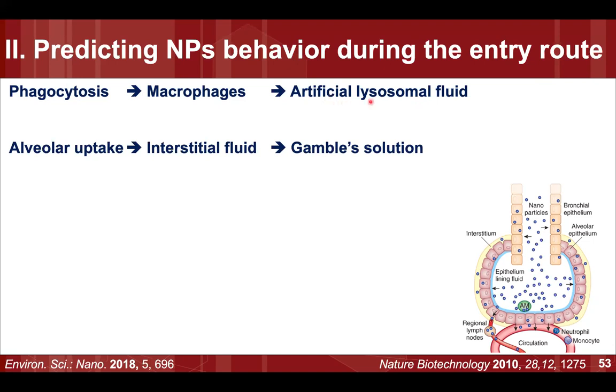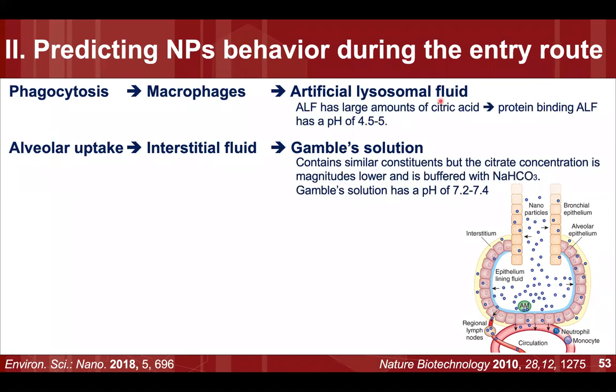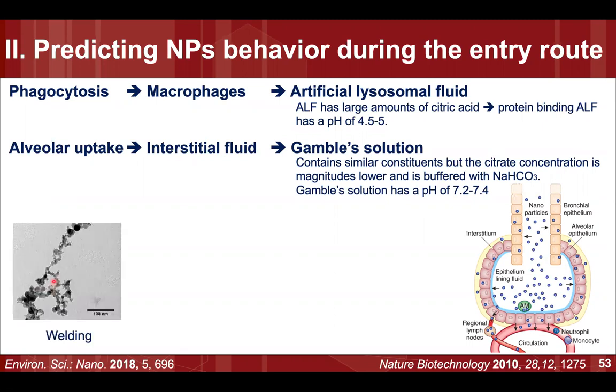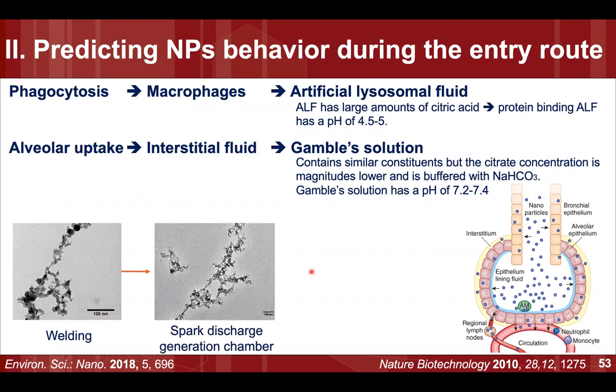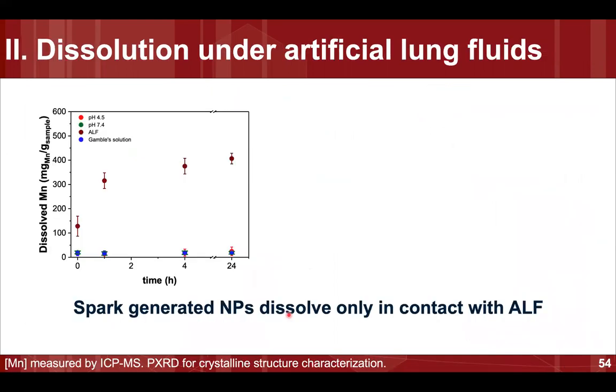One is the artificial lysosomal fluid that is at pH 4.5. We have a lot of organics in there simulating the protein binding that we would expect. And then the Gamble solution, which is around pH 7, also with a lot of organics. And we were trying to mimic the nanoparticles, or the particles, that we found in real-life conditions. This is how they look from the real welding. This is what we were able to generate in a spark discharge generation chamber. And we exposed them to those solutions, trying to mimic the